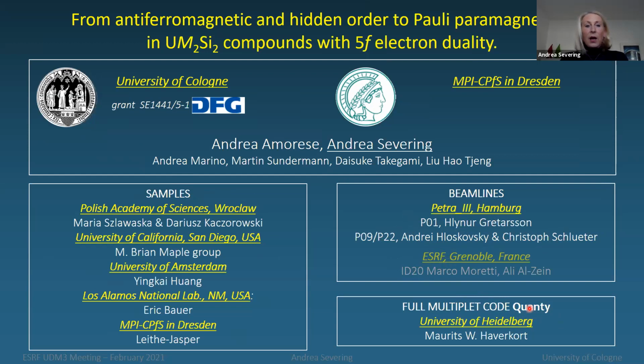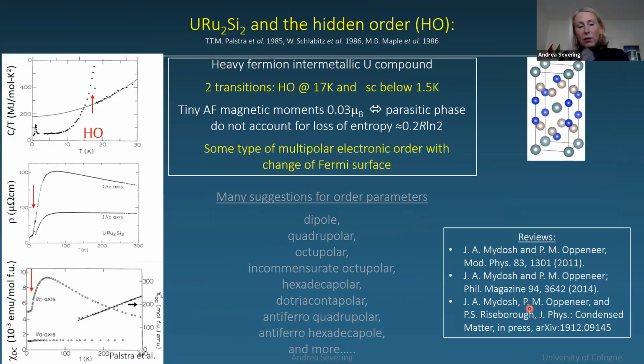So the topic is related to the hidden order in uranium ruthenium-2 silicon-2. It's an old problem. Uranium ruthenium-2 silicon-2 is an intermetallic uranium compound. It's a heavy fermion, and it exhibits two transitions. Here I show the specific heat versus temperature. It has a transition at about 17 Kelvin to some ordered state, and another transition into a superconducting state at about 1 Kelvin. And the mystery is about this transition here.